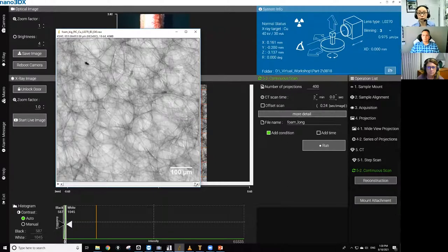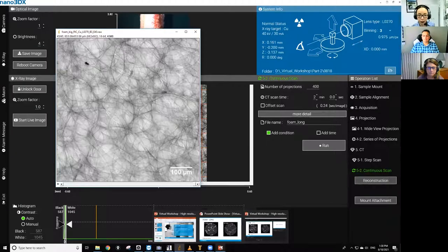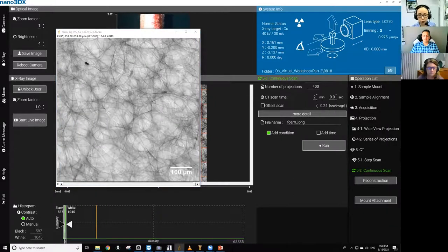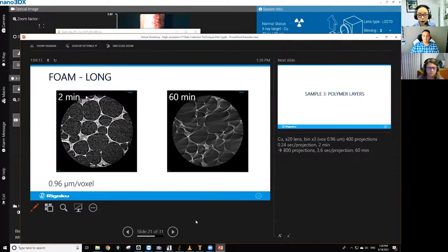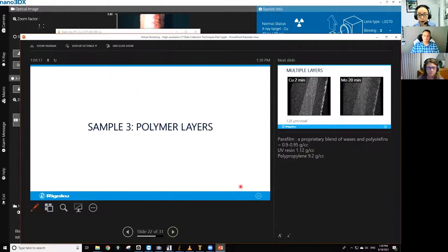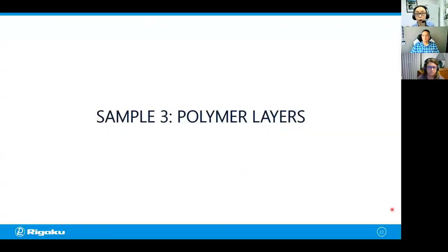Now you know to wait for 45 minutes before you start a 20 hour scan. If the sample moved in the first 45 minutes of a 20 hour scan, there's a good chance that sample movement is going to ruin your 20 hour scan. So this is something good to check before you commit to a long scan. Okay, so that was about the sample movement, and let's move on to the next sample. By the way, I'm using double-sided tape to hold this foam sample. If you are curious about what other materials you can use to hold those small samples for high resolution scans, that's another topic we covered in part one.